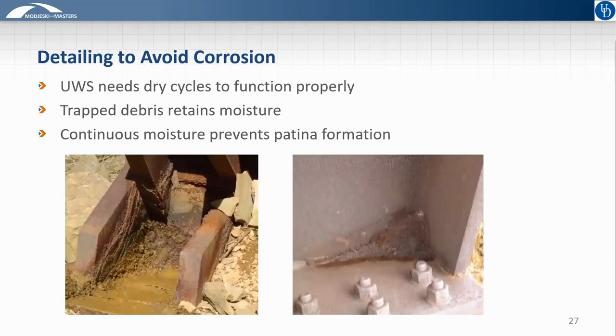So once you've done that and eliminated joints as much as possible, and the joints that you do have, you've tried to control the drainage coming off of them, what else do you need to consider? Uncoated weathering steel needs drying cycles to function properly and to form that patina. It's okay if it gets wet, as long as it then dries out completely. So if you have trapped debris or dirt, pigeon droppings, anything like that, that can trap moisture against the surface of your uncoated weathering steel, that will promote continued corrosion and prevent the patina from forming.